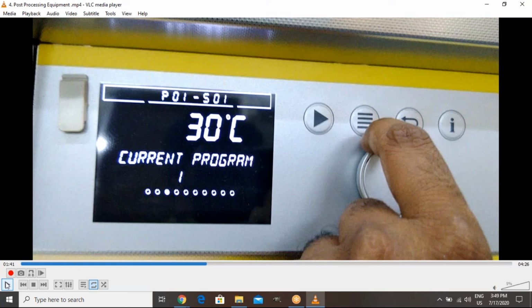So heating means that the components produced from additive manufacturing have very fine grains. So we want to increase the grain size. When we heat with the help of the furnace, the grains grow and combine together. They form large grains, and the heating continues until the grains become uniformly distributed, with new large grains. Whenever it reaches the new large grains, at that time we need to hold for getting a uniform distribution of grains. Therefore, we are using the holding time.